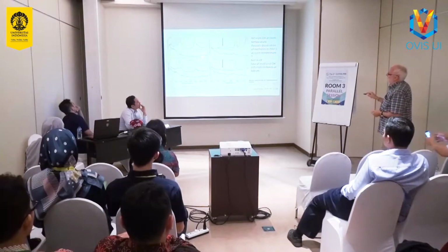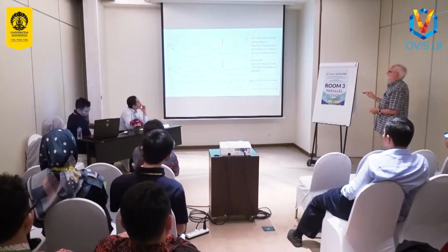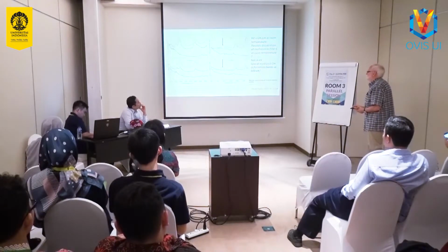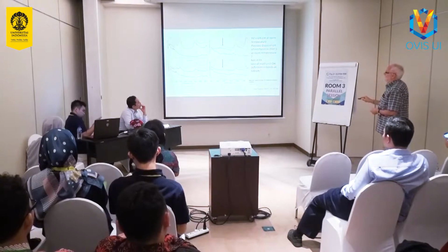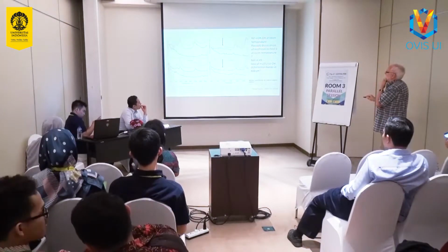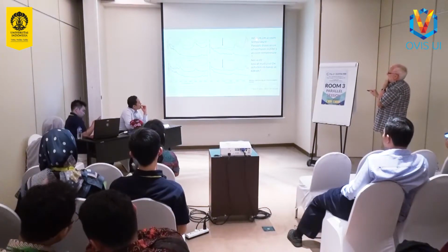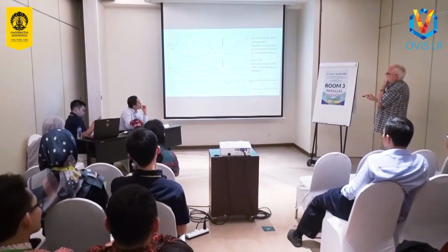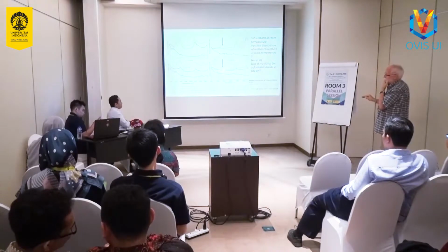The hydroxyl bands have sort of disappeared, although that's a bit hard to see, and particularly the OH bending mode of methanol is broad. We do the same experiment with ZSM5. Here's the ZSM5 empty, there's the OH groups of ZSM5, here's the bending mode. Put in methanol. At first sight it looks very much the same as zeolite Y, but in this case we can't really see that OH bending mode at all.